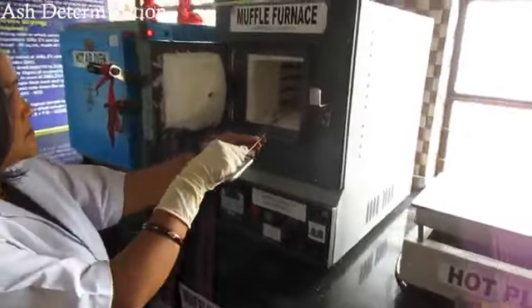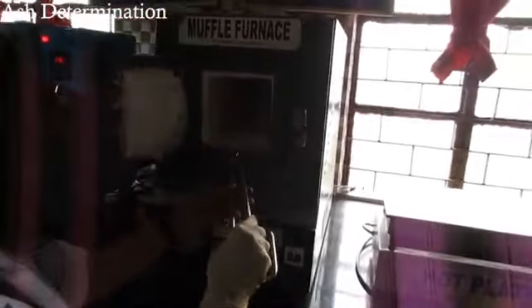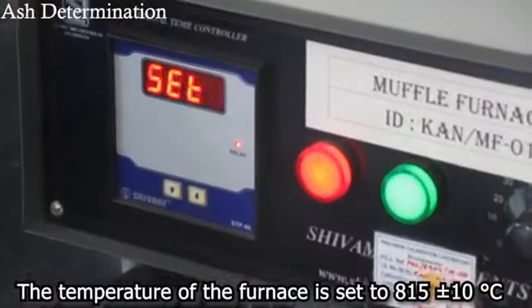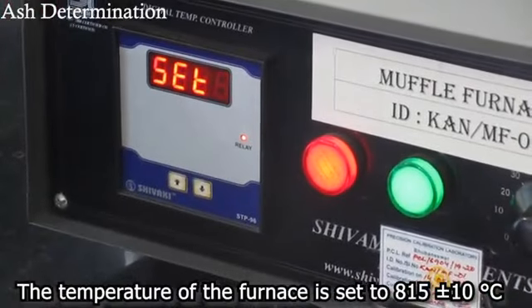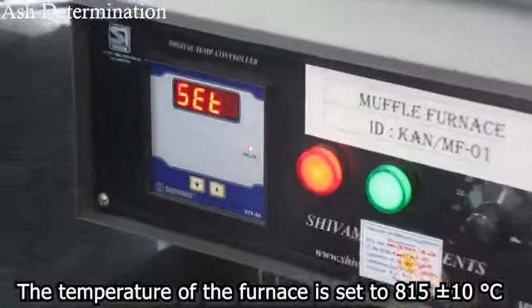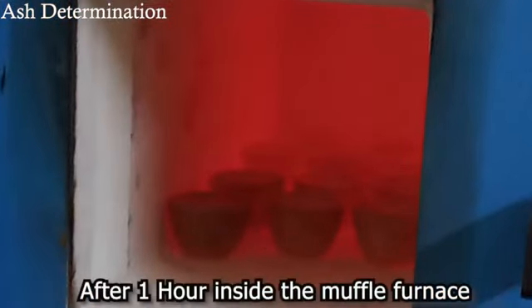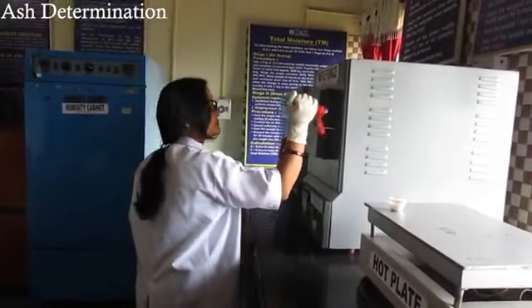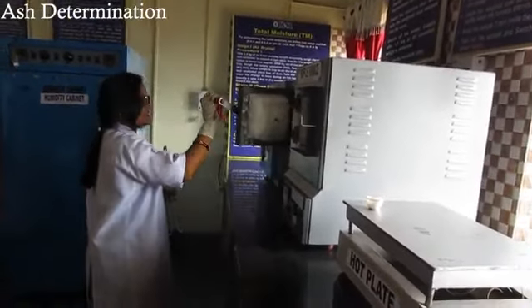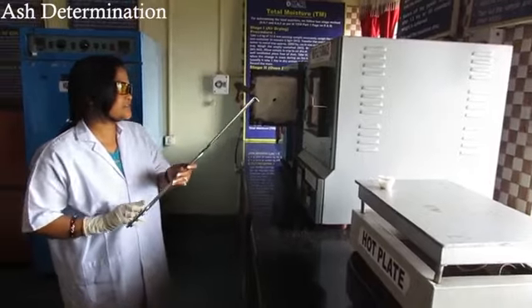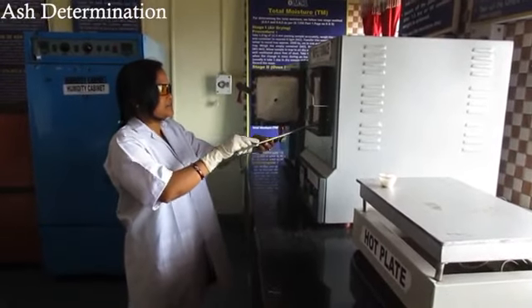The uncovered disc is inserted into the muffle furnace at room temperature. The coal sample is heated in presence of air to 500 degrees Celsius for 30 minutes. Then the temperature is raised to 815 plus or minus 10 degrees Celsius in 30 to 60 minutes and maintained for 60 minutes. After that, the crucible is brought out from the muffle furnace and allowed to cool fast on a cold metal slab for 10 minutes and finally in a desiccator.